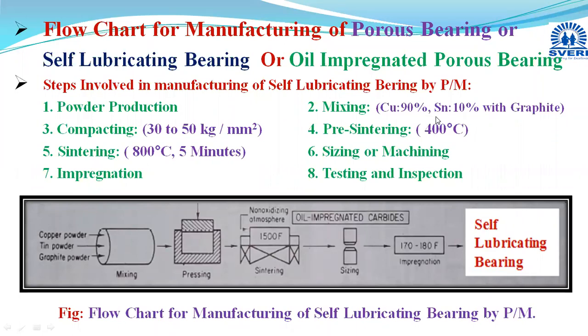And in the third stage, as the tin particles are diffused on the copper particles at a high temperature range, the older grains are broken and formation of new grains occurs. And this is termed as recrystallization and grain growth. After these 5 minutes, the sintering process will get completed with three steps: diffusion, densification, and recrystallization and grain growth. Then, in this sintering stage, diffusion of tin particles will occur on the copper powder particles.